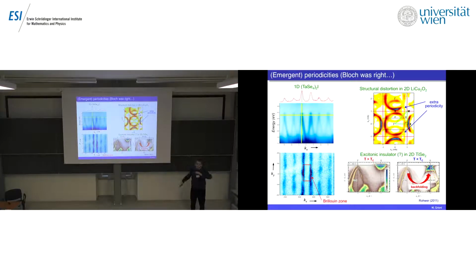This instead is a picture at constant energy of the same system, and you see this is a quasi-one-dimensional material, and the Fermi surface is essentially two parallel lines, and it's repeated in different Brillouin zones. This is another example. This is a two-dimensional material, a free electron-like band here. You see a circular Fermi surface, and actually in this system there is some distortion, and you can see some ghost Fermi surface, which corresponds to an extra, to an added periodicity.